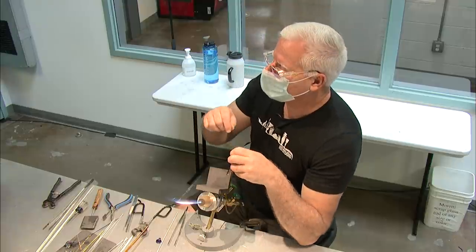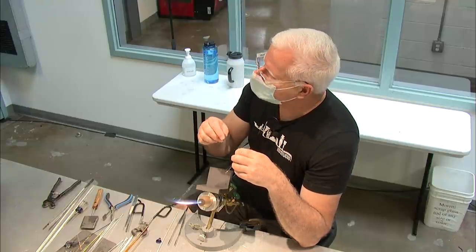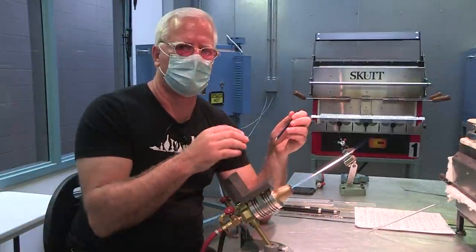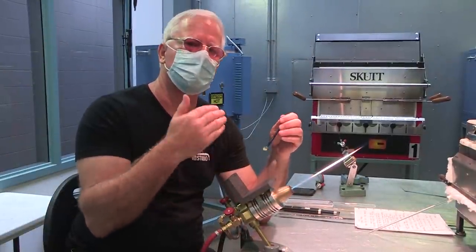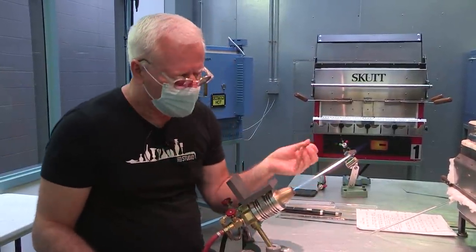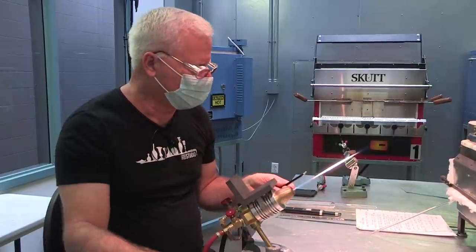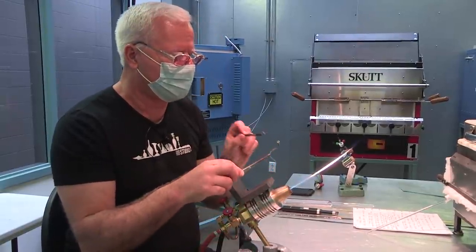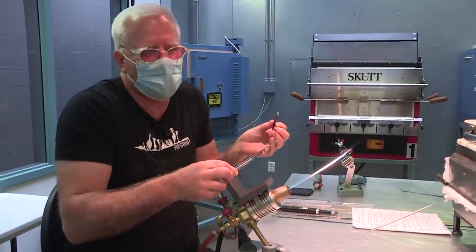And if you get to a point where you're starting to see like terracotta or brown streaking, you know you've stayed too long and the glass is essentially devitrifying because of too much heat for too long of a period of time. So, blue caramel. Your extremes are pretty pronounced. I love this color. I'm not so much a fan of the caramel aspect, but that's just me.